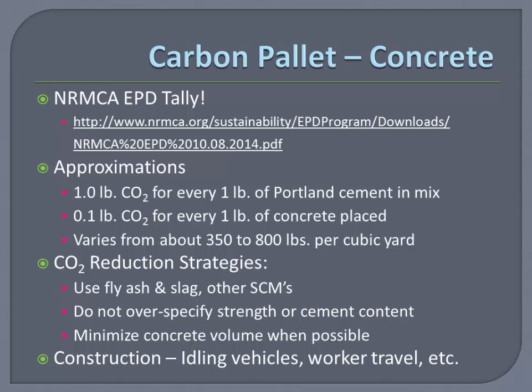Another way to do it is it's about 1/10 of a pound for every pound of concrete placed. So if you are doing it by mass of concrete, that's a way to calculate. And by those numbers, the EPDs show a variance of around 350 to 800 pounds per cubic yard of concrete, with the more cement-rich mixes having the higher content. So there are some strategies that practicing engineers can use to reduce carbon emissions from concrete, using fly ash and slag, making sure that the use of the fly ash and slag actually offsets the amount of cement so that it's not just added on to the amount of Portland cement. You can reduce the amount of Portland that way in a pretty significant way.